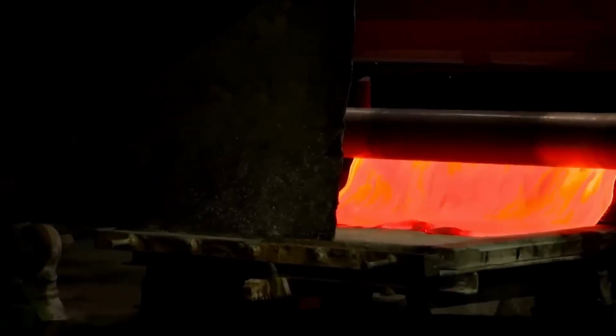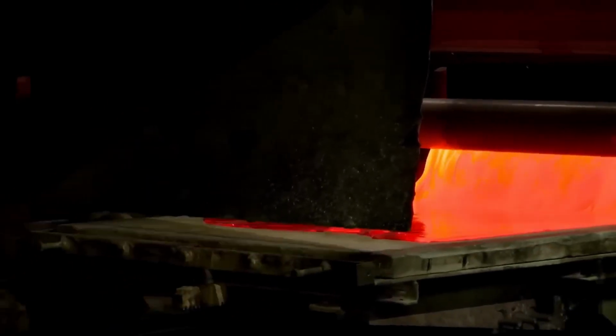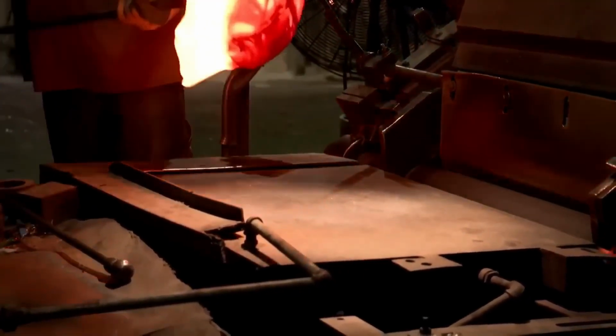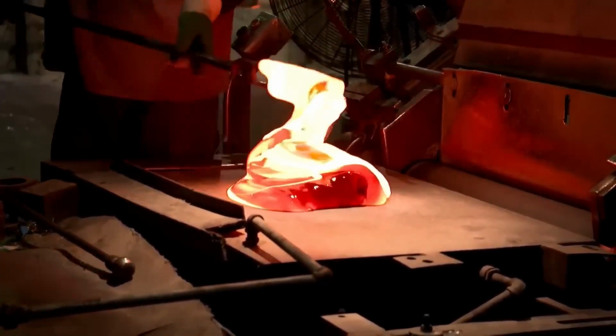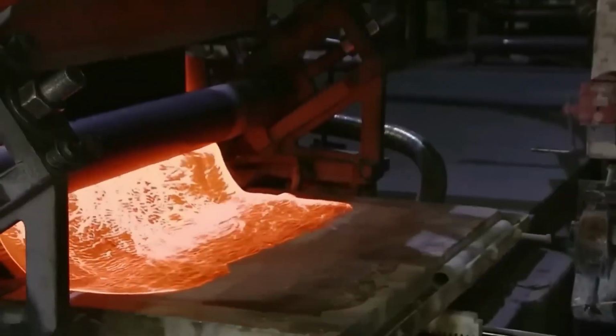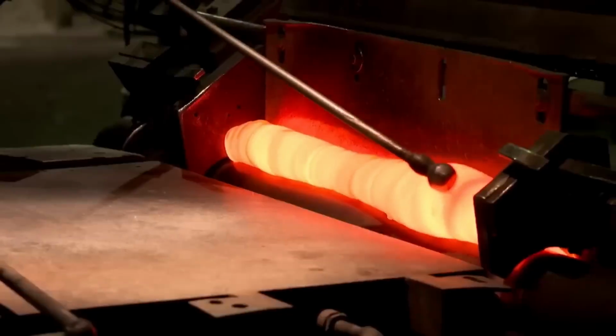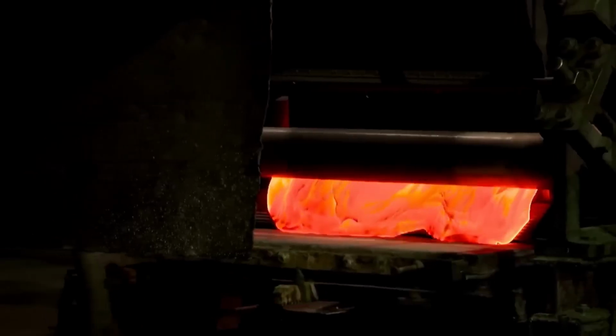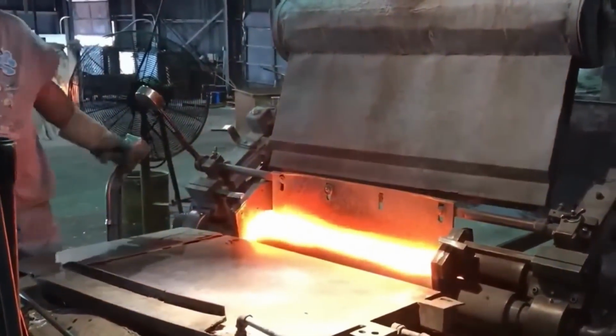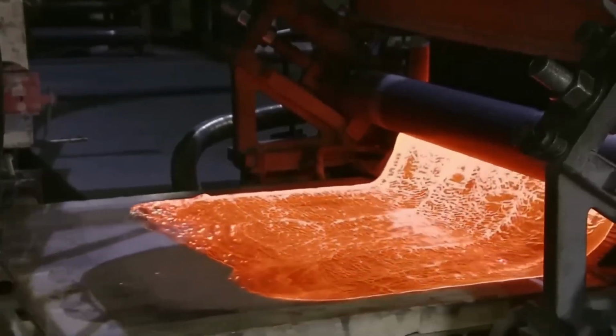But cooling too fast would create internal stresses that could cause the glass to explode later. So it enters the annealing tunnel, where it cools just a few degrees per minute over several hours. The tin bath is kept under a protective atmosphere of nitrogen and hydrogen to prevent oxidation. Even a tiny amount of oxygen would ruin the tin surface and create defects in the glass. The tin itself costs $30,000 per ton and must be 99.99% pure, more pure than most medical equipment.